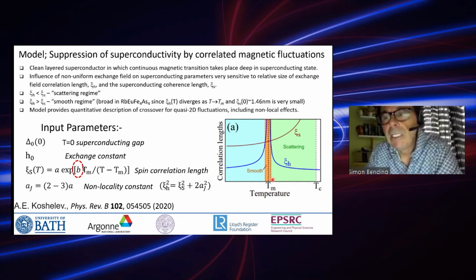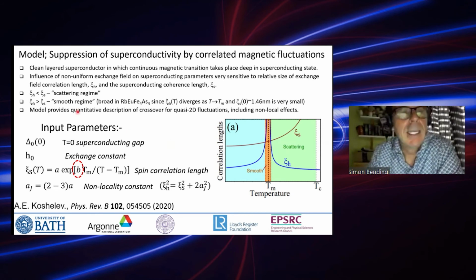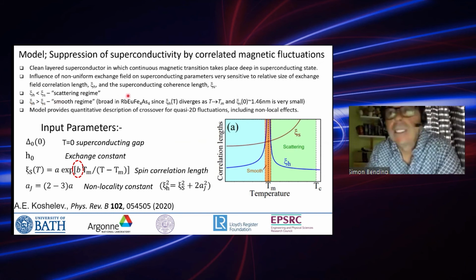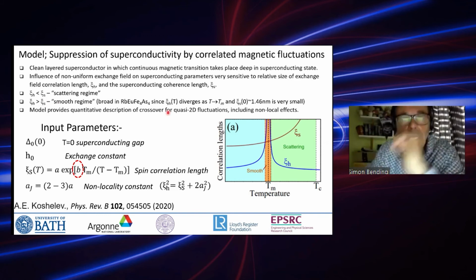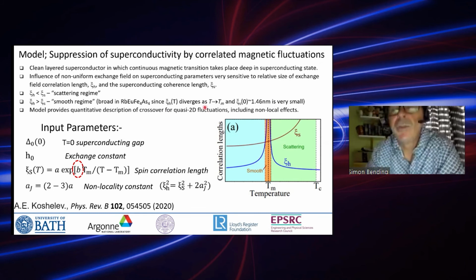What's perhaps more interesting is this region which is indicated in this sort of orangey brown color, and this is the opposite limit where the exchange field correlation length is much greater than the superconducting coherence length. And in fact, in rubidium europium iron arsenide, this is quite a wide regime in terms of temperature, because the exchange field correlation length diverges as the temperature approaches the magnetic ordering temperature T_m, and we're comparing that with the superconducting coherence length, which is anyway very small. The superconducting coherence length at zero temperature is of the order of 1.46 nanometers. So this can be quite a broad region. So those are the assumptions of the theory. There are four essentially input parameters that we have to put into it when we're comparing with it.